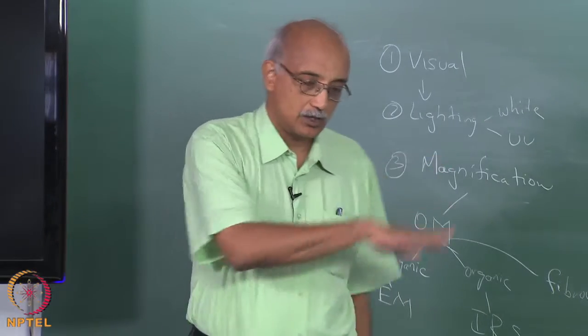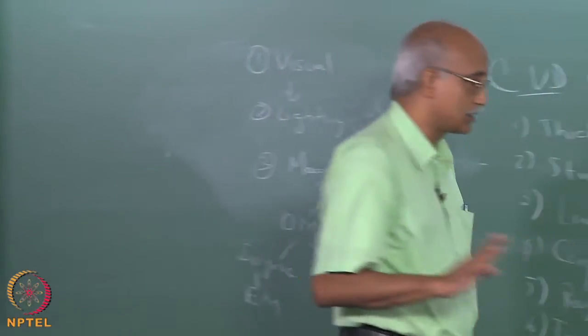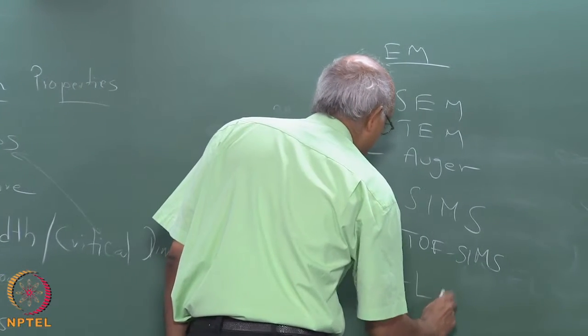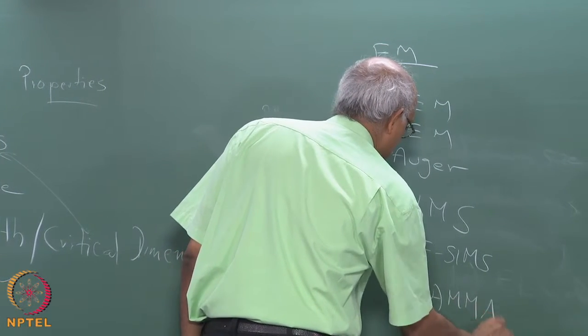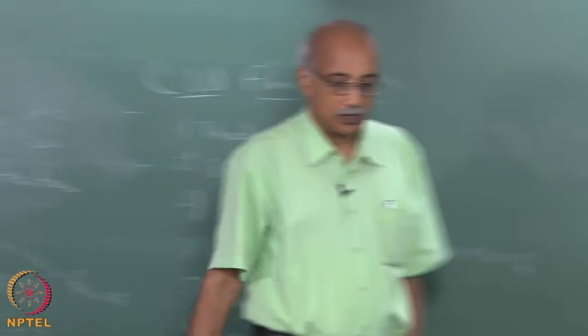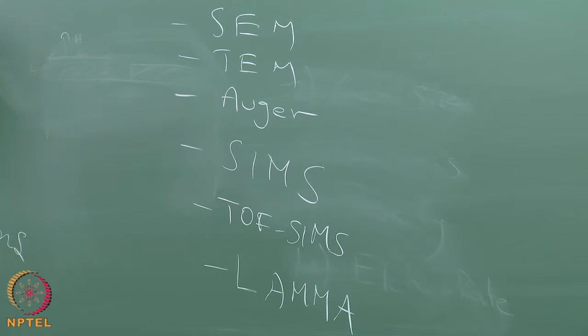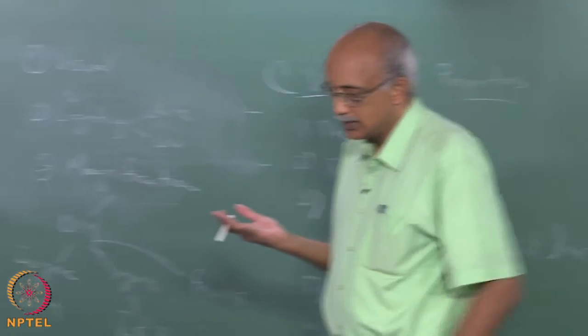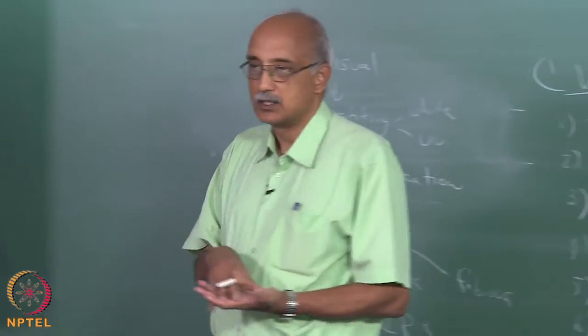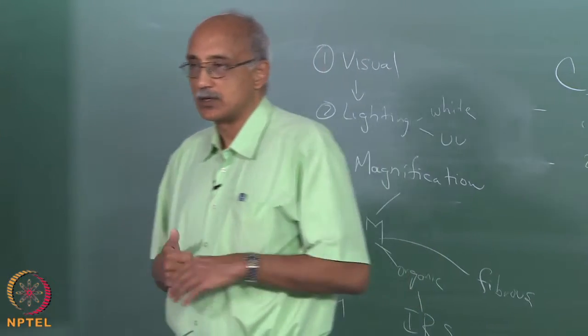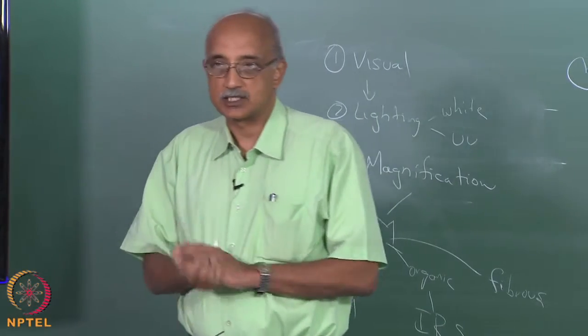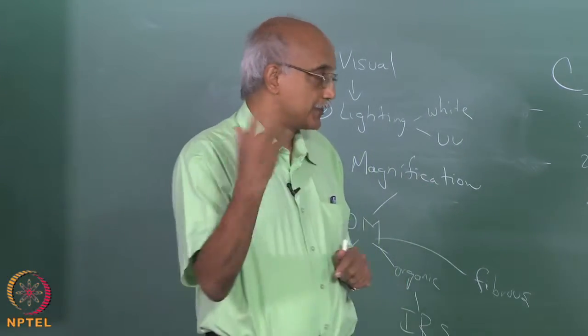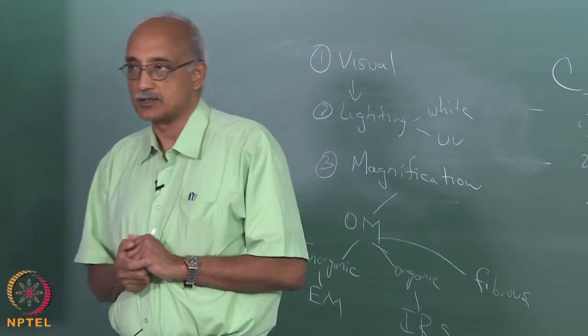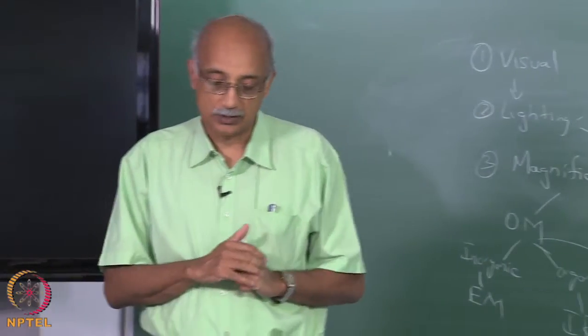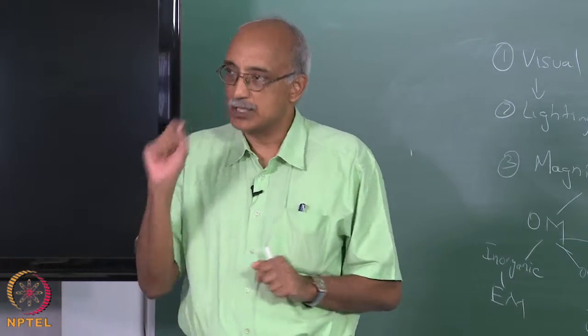So these are all methods that, by the way, there's another one called LAMMA, which stands for laser microprobe mass analysis. This technique, you essentially take the sample and you hit it with a laser and vaporize the entire sample. So you're not just knocking off electrons, you're essentially vaporizing the sample, and the vapors are then taken through a mass spectroscopic analysis and you detect the elemental composition. So all these techniques are good for looking at which elements are present.